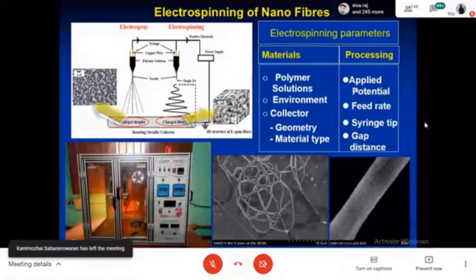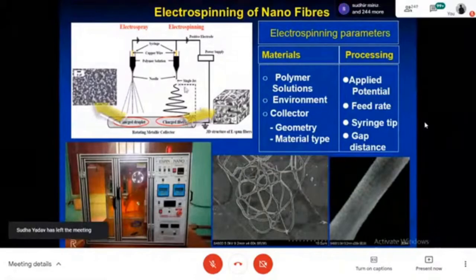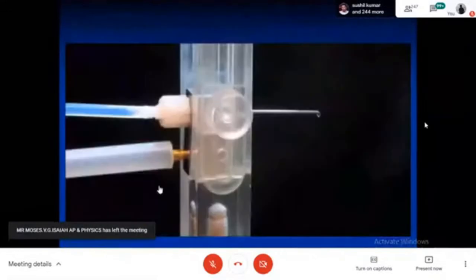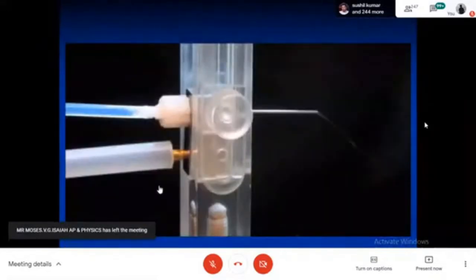And actually there are a lot of parameters to be optimized here: the applied potential across the tip, and of course the other end is connected to the metallic collector here, the rate at which the solution is coming out of the nozzle, and also the distance between the nozzle and the collector. These are all the parameters to be optimized. And the typical electrospinning system looks like this, and this costs about 4 to 5 lakh, because the major cost is the